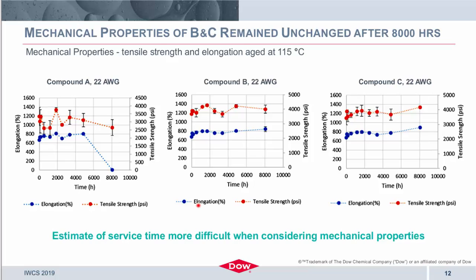In this case, we were looking for a given, quote, failure time of roughly 50% loss in retention of the properties. And so what I show here is, again, the elongation as a function of time on the left axis, tensile strength as a function of time on the right, for compound B and C on the larger 22 gauge wall.